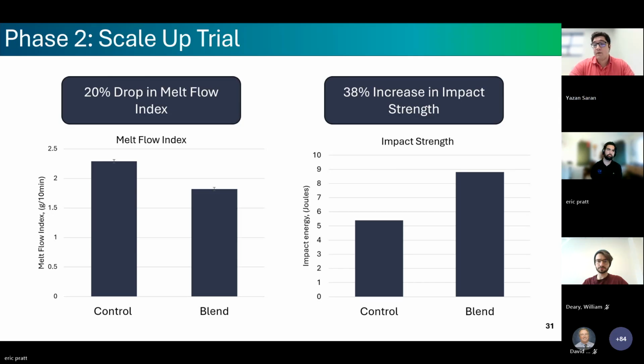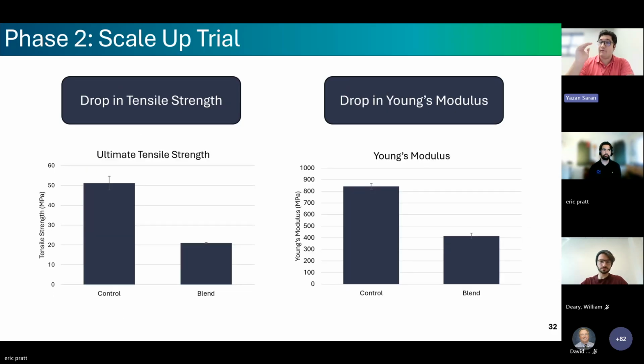After that, we performed the same drop impact test as before on our new blend, and we found a 38% increase in impact strength, a result that was both exciting and anticipated with an impact strength of almost 9 joules, well above the 5.4 value of our baseline polypropylene.